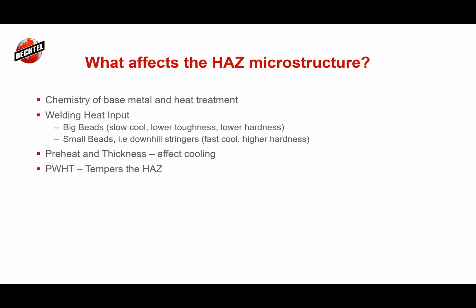But I had a few older gentlemen that had gone up to Canada 10 years ago, and they said, why aren't we still doing the 6010 downhill wash? And of course, in Canada, it was higher strength materials. With that lower temperature, when you do that 6010, that really high heat and then fast cool down, it was giving them all martensite underbead. And that's just not the right way to treat some of the higher strength carbon steels where you're getting that susceptible microstructure.